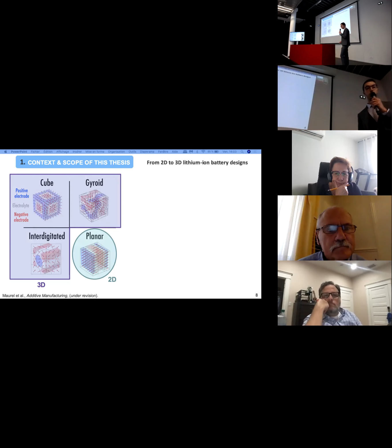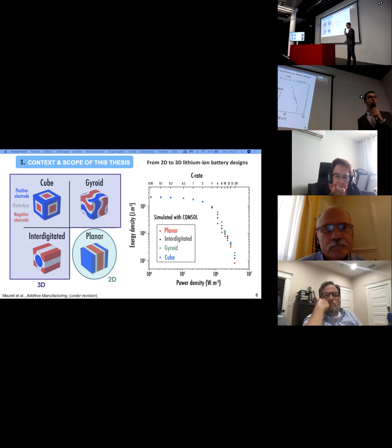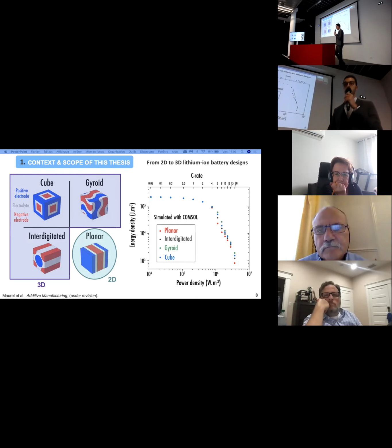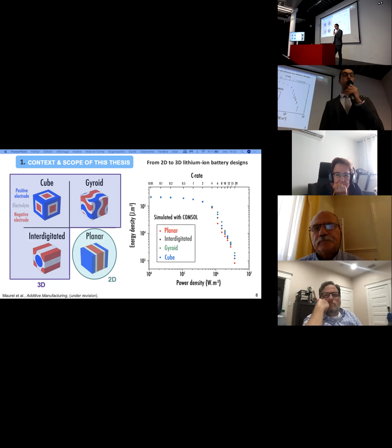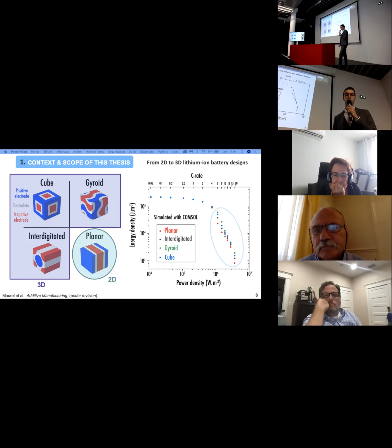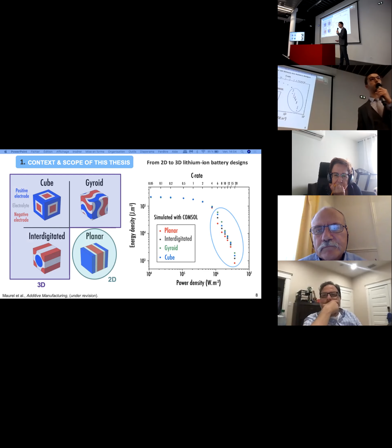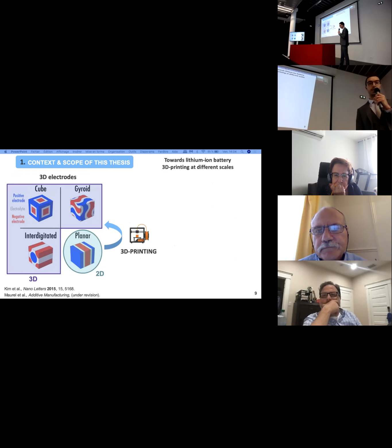And so based on the results that I'm going to present today in this presentation, and the results from the thesis, we were able to model and simulate a Ragone plot, so energy density versus power density. And here, indeed, at high current density, so for power applications, we were able to demonstrate that we have better performances for three-dimensional architectures compared to 2D ones.